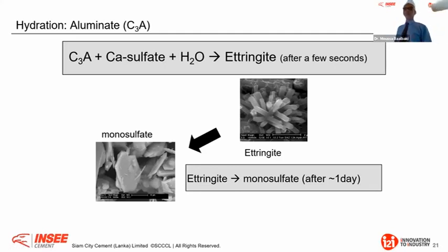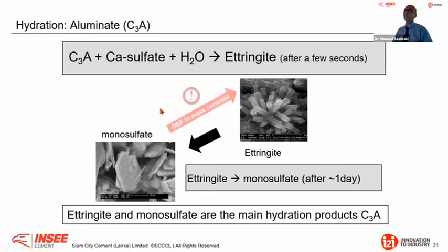But one important thing: at the first knowledge sharing session, Professor Nanayakkara was talking about mass concrete. In mass concrete, we can have a problem if we don't control the temperature. We can stop the formation of ettringite at early age and we form what we call delayed ettringite formation. Therefore, we form monosulfate instead of ettringite, and later with age, after 1 year, after 2 years, this monosulfate will go back and form tri-sulfate again. And you see, these are very long needles. They will exert huge tension in the concrete, and this very high tensile stress will develop cracks in your concrete. This is why we call it delayed ettringite formation in mass concrete.